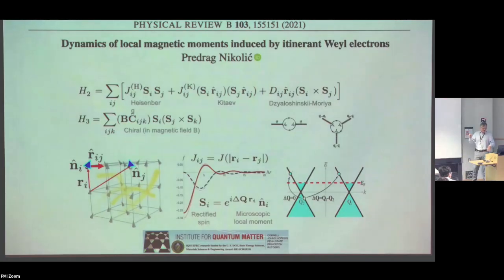So I'm going to say a little bit more about these results. This is one of our good colleagues who's adjunct at the University, Predrag Nikolic, and he has developed a really beautiful analysis of this kind of Weyl-mediated exchange interactions, but where he uses the simplest version that you could have of the Weyl band structure. So just a k·p type analysis of the electronic band structure. And what he finds is that in that case, the Dzyaloshinskii-Moriya interaction takes this form where the vector is always oriented along the bond that separates the two spins. So that is what comes out from that electronic band structure.